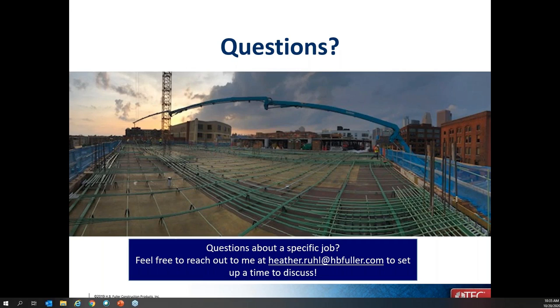So you might think it is, but a lot of times what that actually does is it removes moisture that's needed from the patch. So again, we talk about there's a certain amount of water you need for concrete to react. And it's the exact same with any of the patch or the self-leveling products, right? So if you install a patch that you've mixed with water and then you put a fan on it, what that fan does is it removes the water that you put in it. And while it might seem like it dries faster, what you're going to end up with is underwatered patch, which is typically a lot weaker and it doesn't have the same integrity that a patch that was allowed to dry normally does. There are very few products that we will ever suggest putting a fan on. And typically if we do, it's indirect. But again, especially patch, any of the concrete products, typically a fan's not the best way to cure it.